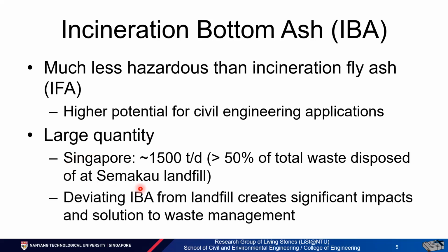In Singapore, the daily generation of IBA is more than 1,500 tons per day, representing more than 50 to 60, 70% of the total waste disposed of at the Semakau landfill. Therefore, if we are able to deviate IBA from landfills, we think that will create a significant impact and solution to the waste management plan and strategy locally in Singapore.